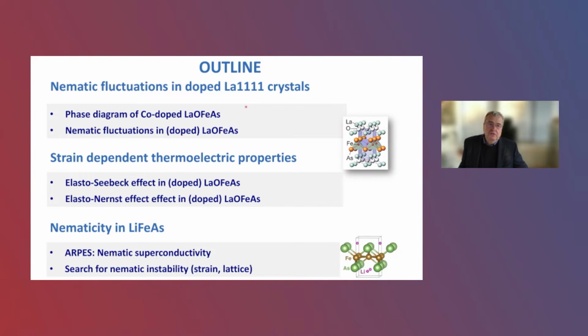I will show you phase diagram now on single crystals, which we obtained for first series of these 1111 type crystals, and discuss in particular the nematic fluctuations, and arguing that there is a very strong coupling between these nematic fluctuations and superconductivity, which points to the real role of orbitals in these systems. I will show you some recent experiments where we measured strain-dependent thermoelectric transport, so where we have a direct access to changes of Fermi surface and scattering upon tiny changes of the lattice structure, so an intimate coupling between lattice and electronic degrees of freedom.